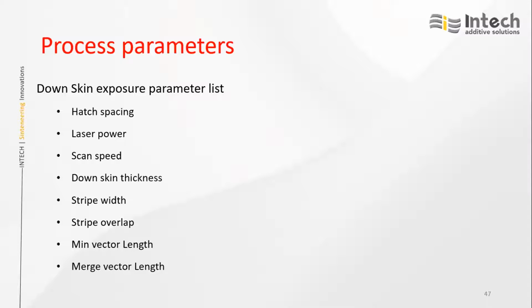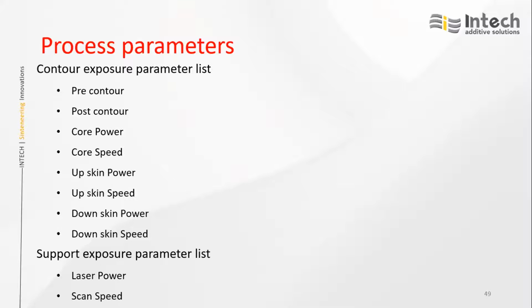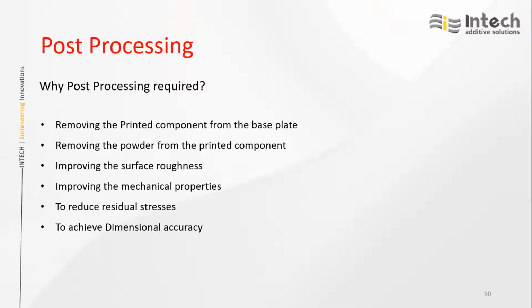In a similar way, downskin has many process parameters, upskin has many, and contour and support will have all these parameters too. When you want to produce a component that is good and defect free, this number of process parameters we need to optimize - it's almost 100 to 150 process parameters. Out of all these, the 4 parameters - power, speed, hatch spacing, and layer thickness - are very important, about how we need to arrive at energy density and how the process parameters need to be optimized.